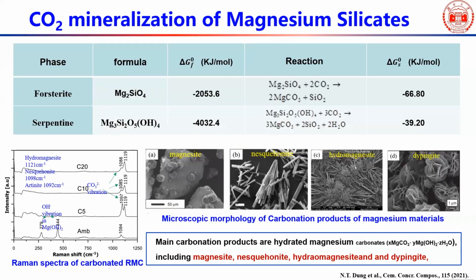And then we also tried to understand the carbon mineralization of magnesium silicates. Quite a lot of work has been published by geologic people. Initially, they tried to mineralize carbon through the reaction between carbon dioxide and olivine and also other materials like basalt. But on the other hand, mineralization using those materials needs very high pressure and a very high temperature.